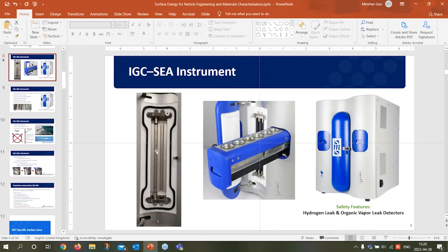And for the comparison between the IGC and DVS, for example for the BET surface area, it always gives very similar results, or at least the trend between the samples, which has a larger surface area and which has a lower surface area, is quite similar as well. And we normally use the same probe molecule to determine the BET surface area. So if we are using octane as the probe molecule for the IGC technique, we normally do an octane isotherm for DVS as well.